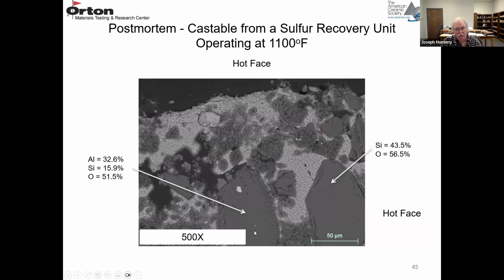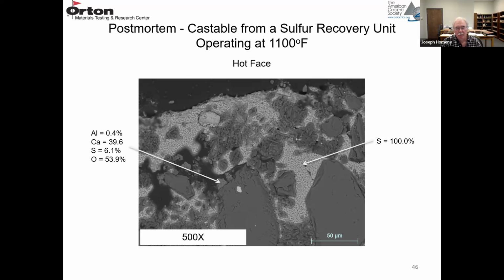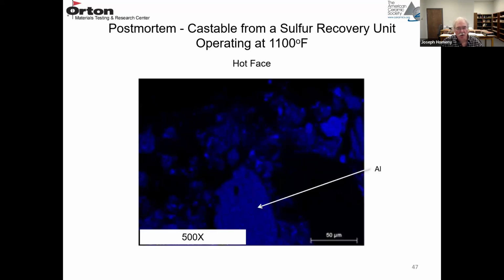And then just a higher magnification right at the hot face. This has to be a residual quartz because it's all Si and O, so silicon and oxygen. And this is an alumina silica aggregate. So there's alumina, silica, and oxygen. And then the lighter phase is the sulfur. If you look at the chemistry of the lighter phase here, it's all sulfur. And then this area here, it's a little bit lighter gray than the coarser aggregate. That has calcium, sulfur, and oxygen. So that's probably the calcium sulfate. There was much more elemental sulfur than calcium sulfate at the hot face.